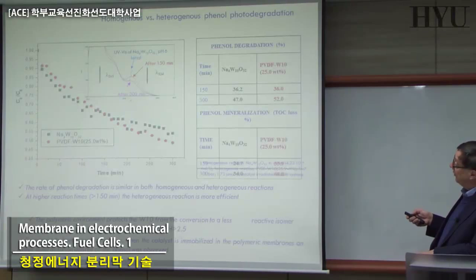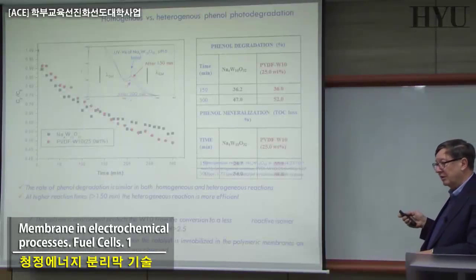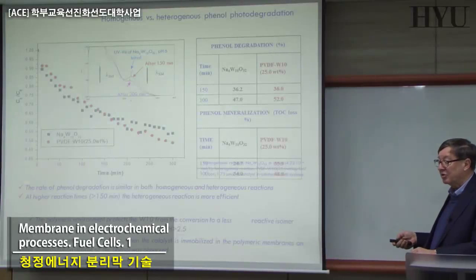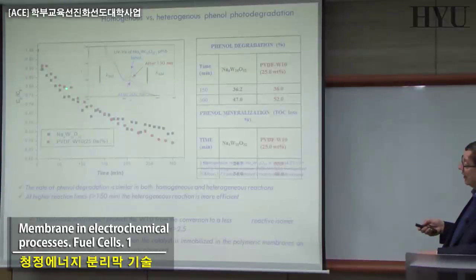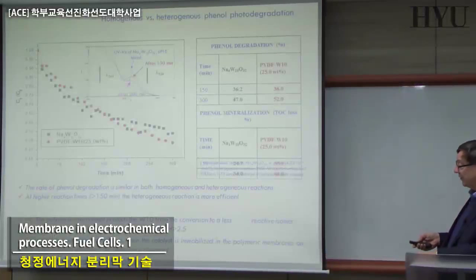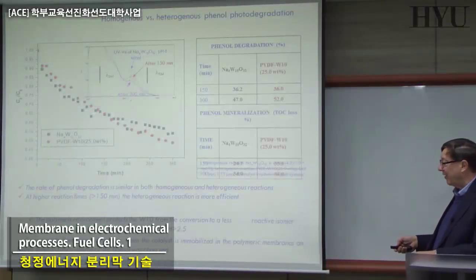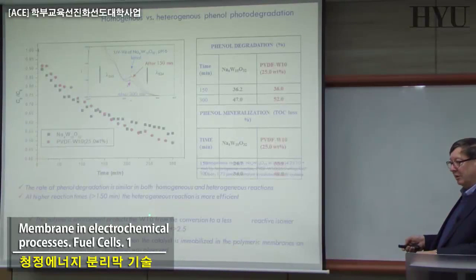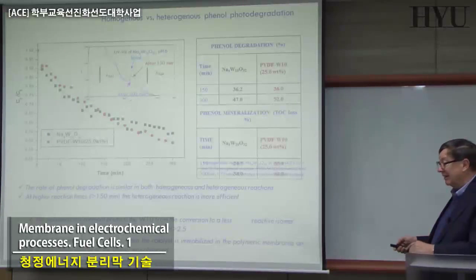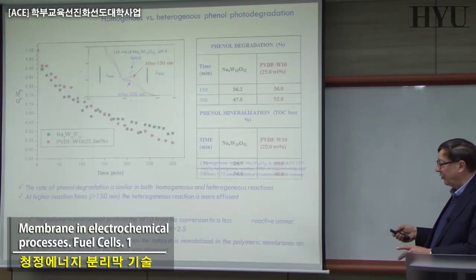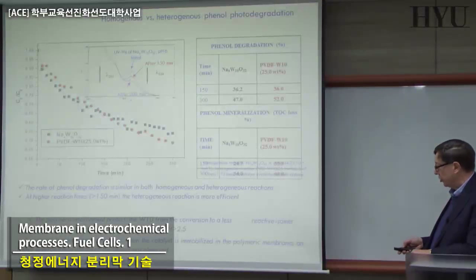By the way, this is a comparison between the homogeneous and heterogeneous degradation. And you can see here that the heterogeneous degradation is giving more interesting results than the data that we can normally have in a homogeneous system. And the efficiency, particularly in terms of lifetime, the polymeric environment can be considered a system to protect the properties of the catalyst, much better than just having the system free in your homogeneous system.